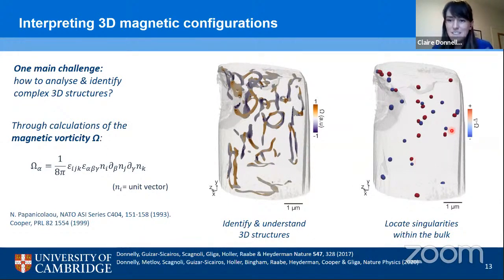And I think this is a really nice demonstration of how powerful this new type of data processing is. Here with this simple calculation, we see over 50 Bloch points popping up out of the data set. Whereas if you remember back to our previous analysis, we were looking at a sub-volume, at the crossover points of a vortex core and a domain wall, and in that way we were able to identify two different Bloch points within our structure. So this is a really useful and powerful technique for the analysis of such configurations.